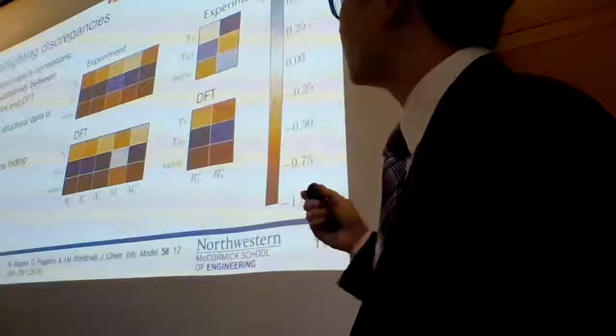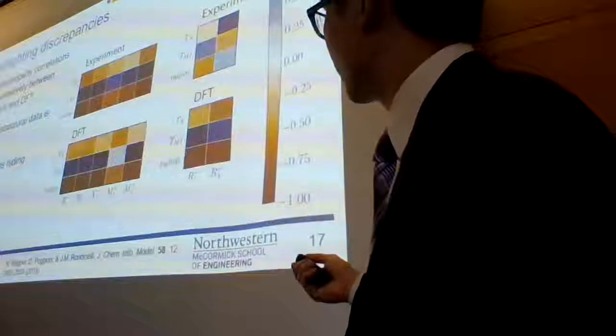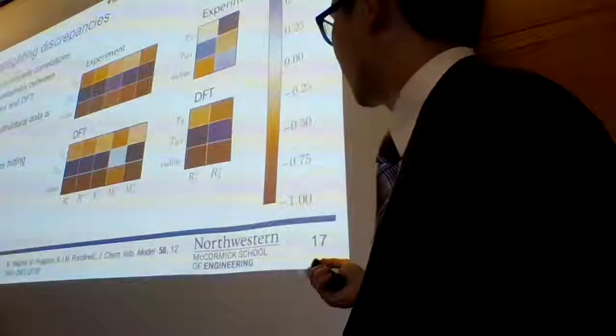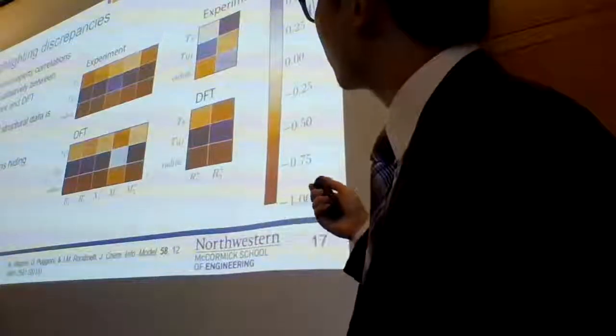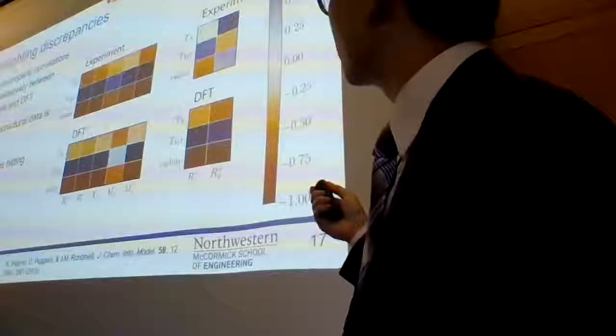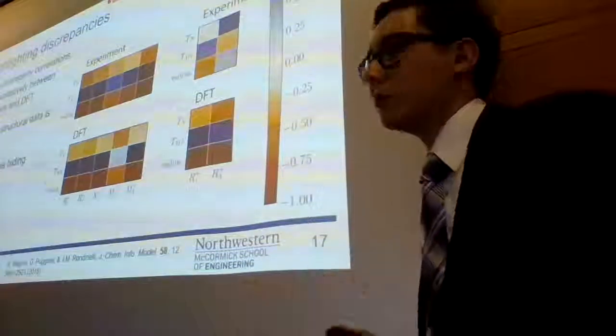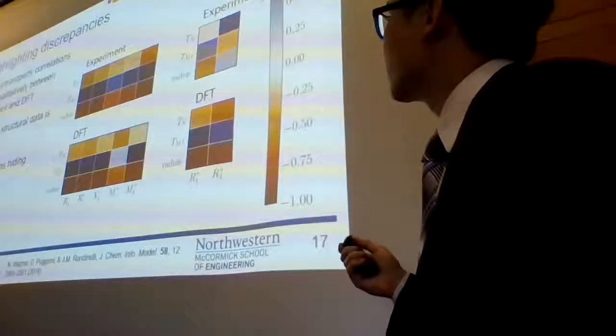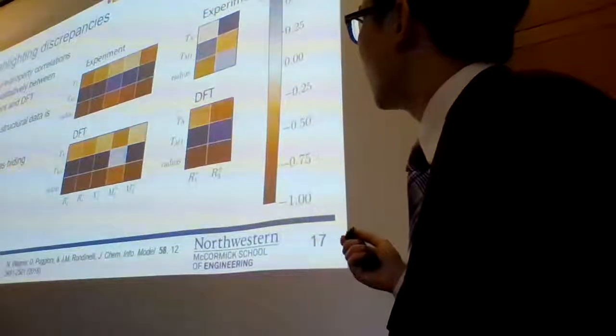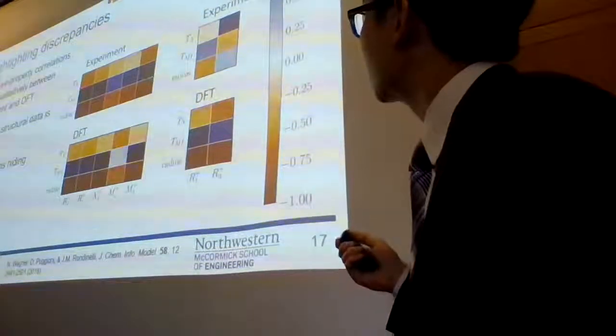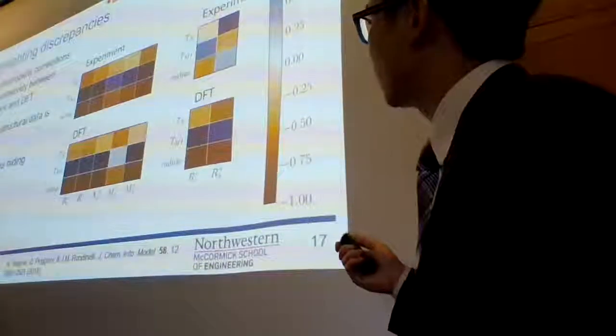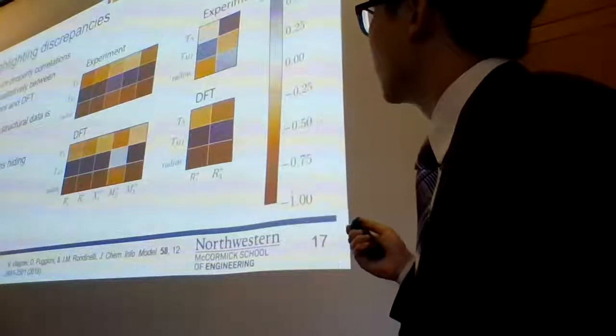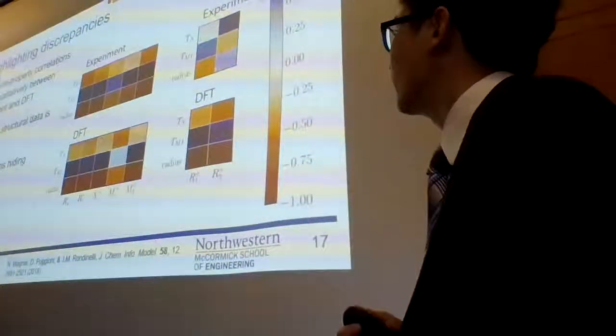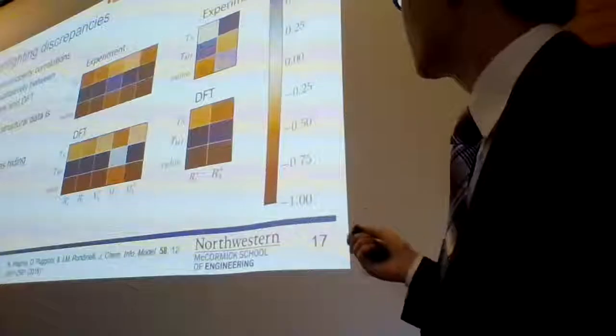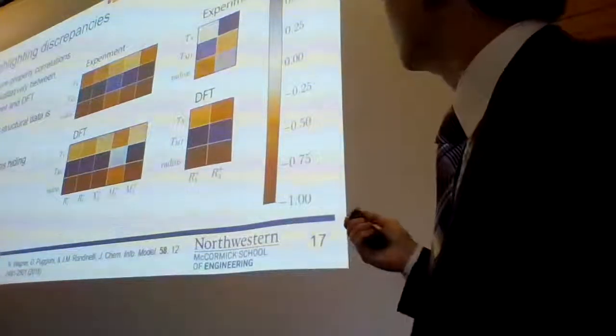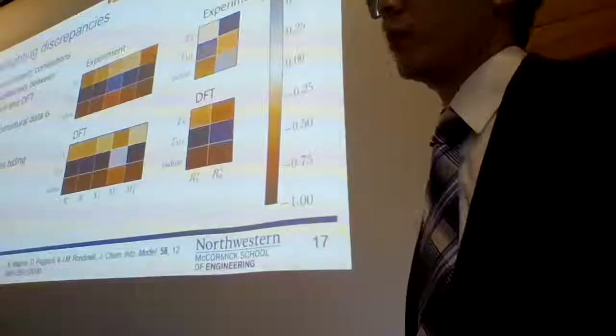But the interesting thing is these modes I mentioned earlier, this R1+ breathing mode, which is related to the charge ordering, and this Jahn-Teller mode, actually differ: the correlations differ between experimentally reported structures and those computed using density functional theory. So if you were to talk to your experimental colleague and they were to say, how do I boost the metal insulator transition temperature, in one case you would tell them, well, you should try to pump this Jahn-Teller mode with a laser or some ultrafast excitation source. And in the other case you would say, actually, no, you should try to inhibit it.